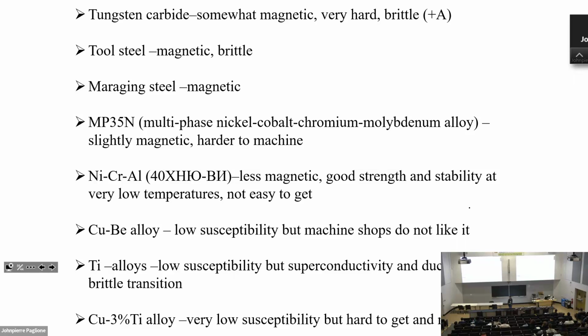I asked ChatGPT why you use this instead of beryllium copper, and it didn't give me a very good reason. Eventually, I found a Japanese paper, but it's all in Japanese. Then ChatGPT translated it for me. So I finally figured out this one at room temperature is not as good as beryllium copper. However, at very low temperature, it has very good strength and stability, according to that Japanese paper, which I cannot understand. And in terms of magnetism, this one has nothing magnetic. This one might be slightly magnetic, but better than this.